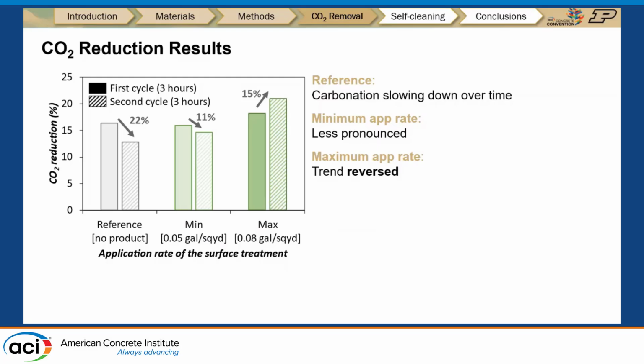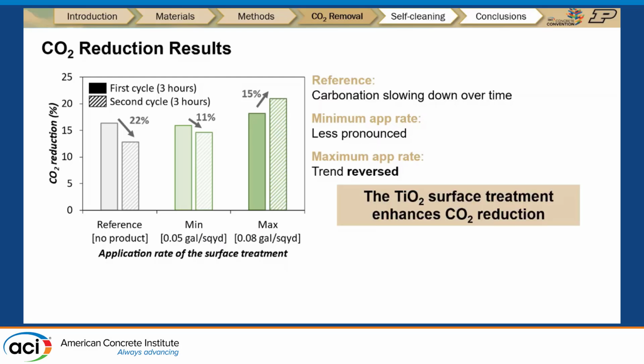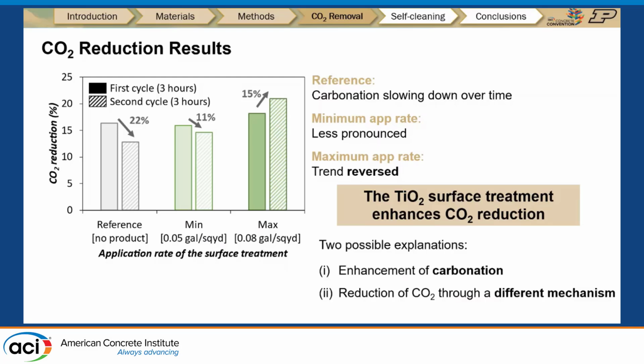And this is expected and reasonable because the carbonation is actually slowing down over time. And in the minimum application rate, we see that the trend is less pronounced. And finally, in the maximum application rate, the trend is even reversed. So the titanium dioxide surface treatment did enhance the carbon dioxide reduction. There are 2 possible explanations for that. One is that the carbonation is enhanced by our surface treatment, or there is a different mechanism helping with the reduction of carbon dioxide.